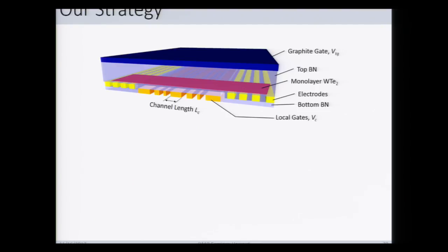So I'm going to go slowly. There's a lot of things happening here. At the bottom in orange, we have these finger gates that are long and narrow. And each of them has a different length in this dimension that we're going to call the channel length. On top of this, we place our boron nitride dielectric that we then, on either side of the gates, on top of this dielectric, we place these electrodes. Everything is designed so that the height of the electrodes matches the height of the boron nitride in the center, so we can have a nice flat device structure.